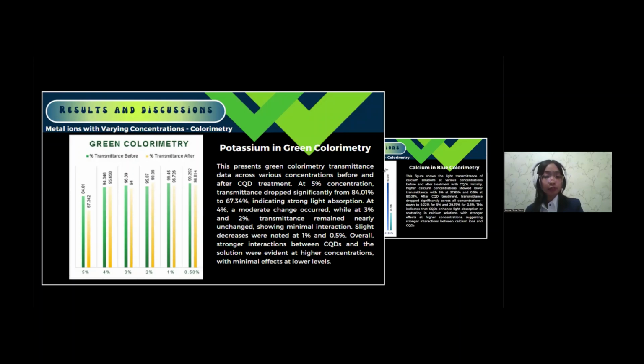At 3% and 2%, the light mostly stayed the same, showing very little interaction. At 1% and 0.5%, there was only a tiny drop, so the effect was minimal. Overall, stronger effects happen at higher concentrations, while lower ones barely change the light.